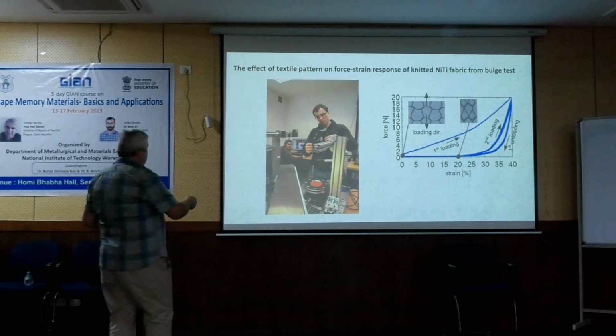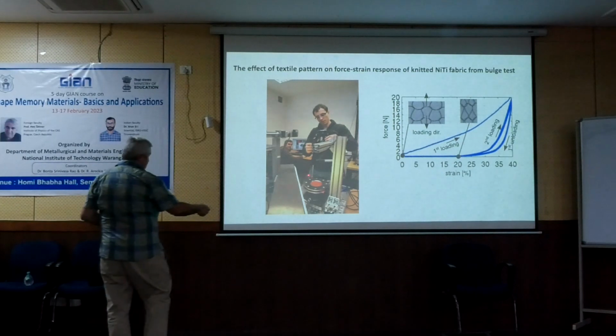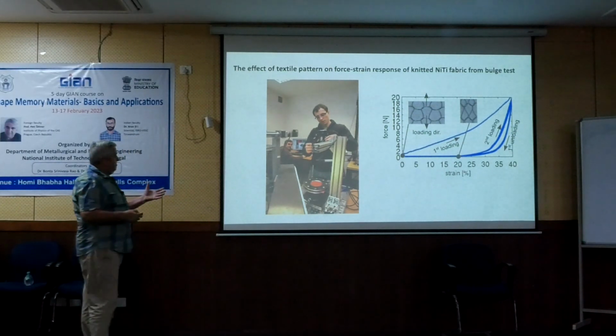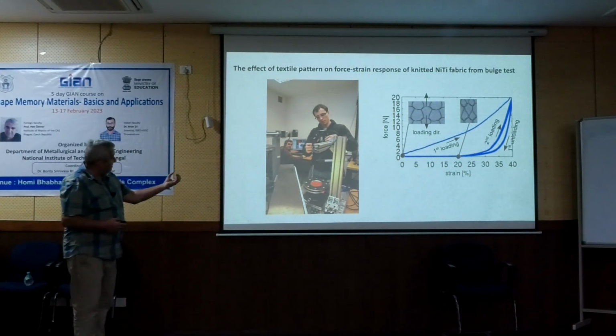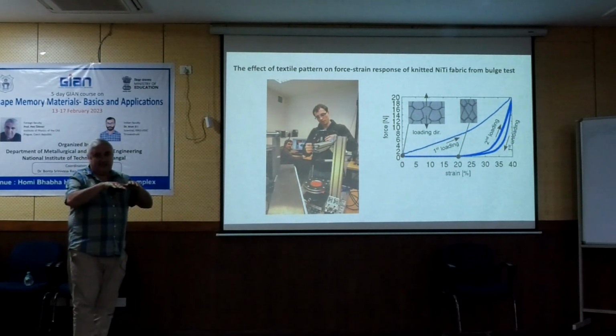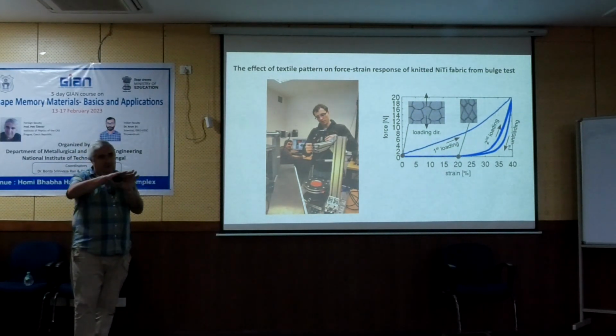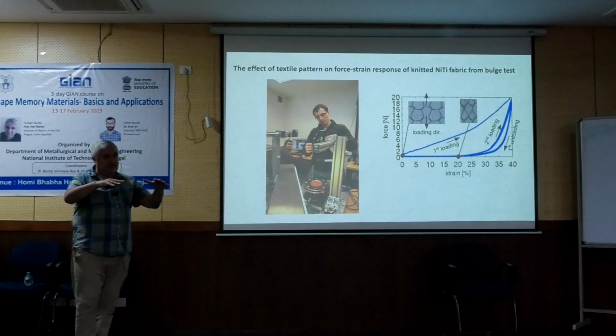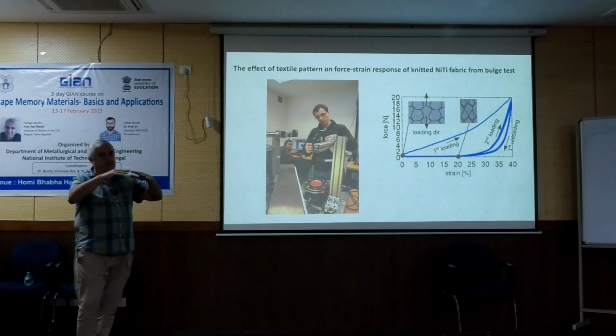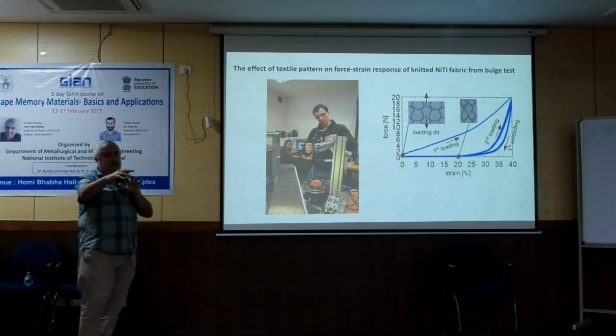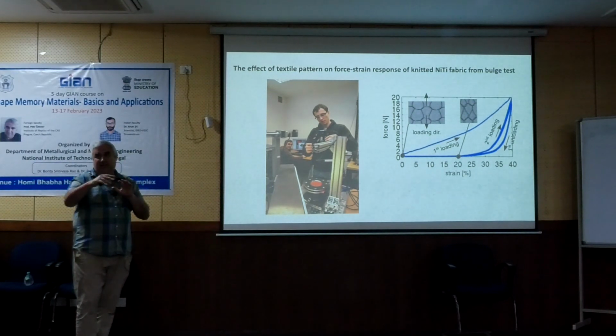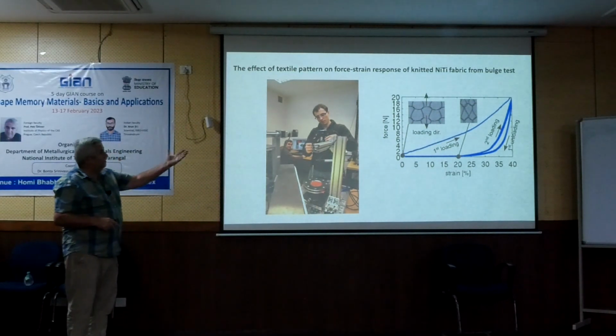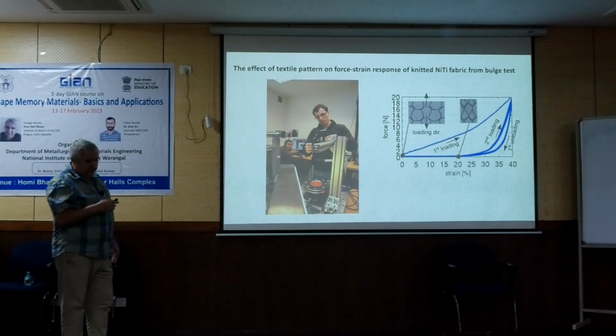What we liked was a bulge tester, which is here. So we made some kind of pressurized chamber underneath, and there was a piece of rubber on top of it, and we put the textile on it, and when you pressurize it, the textile started to be expanded in biaxial state, and with this we practically did most of the experiments.